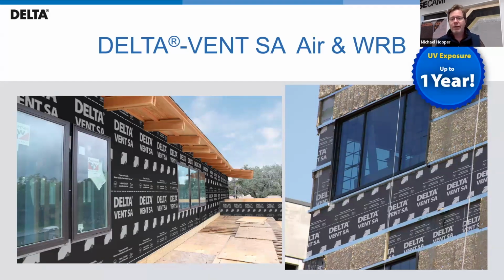I should mention our air barrier recently changed. It used to have a gray facer. When we changed the performance layer in between, it increased the ability for it to resist UV degradation. So in climate zones 3 and above, this has been tested and can be used for applications with exposure times up to a year.